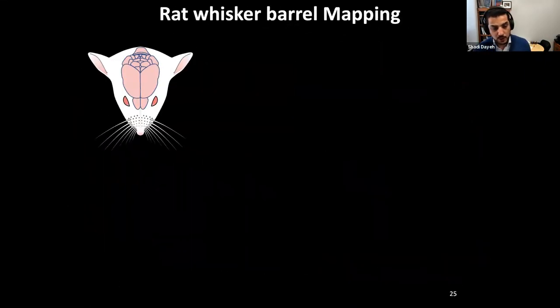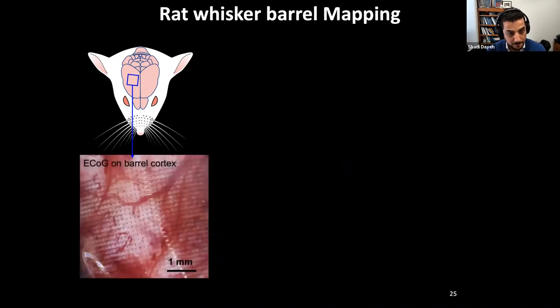When we do the recordings, we usually reject the recordings from channels that have an impedance of 100 kilo ohms or more. And that's because these higher impedance channels will couple noise. So we really would like to have a very narrow distribution of the impedances of the contacts to start with.